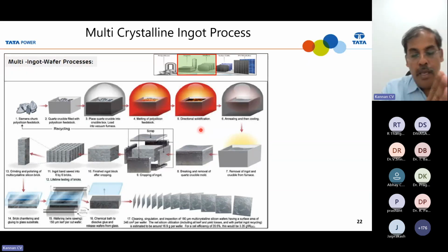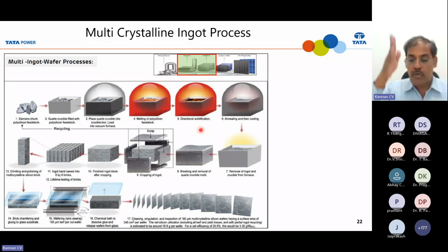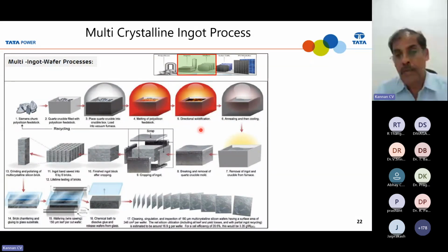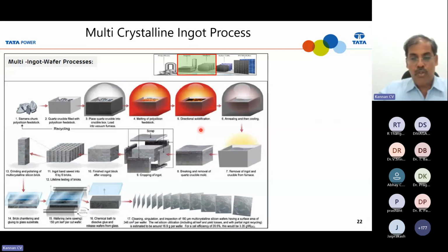from bottom to top. And in this case, you can load more amount of crystal, because based on the crucible size, you can mix more amount of raw material. Also, you can grow big crystal, then you can cut according to the wafer size, whatever wafer size you want, right? But one of the disadvantages is a multi-crystalline growth, and the crucible walls are highly contaminated.